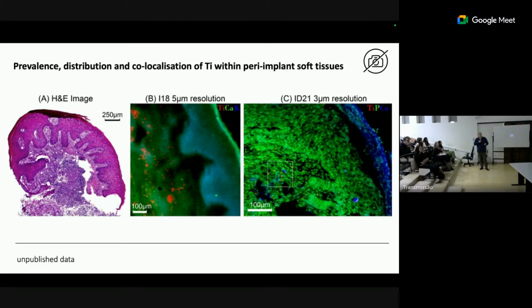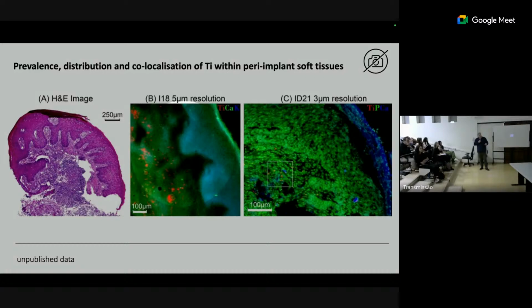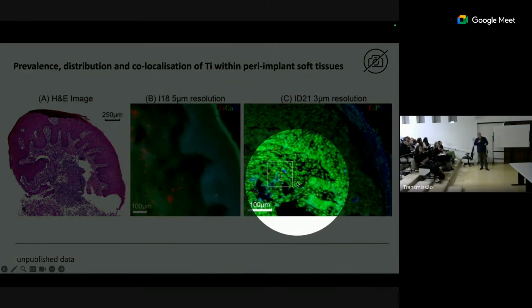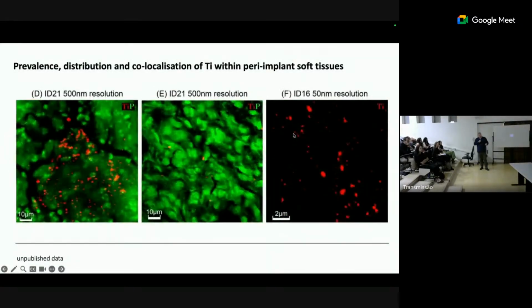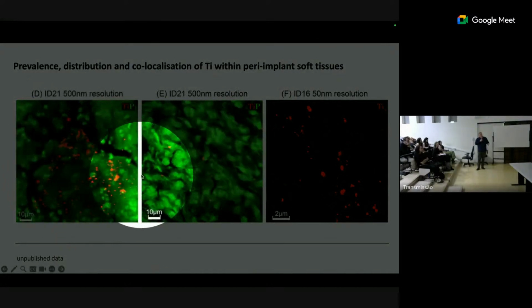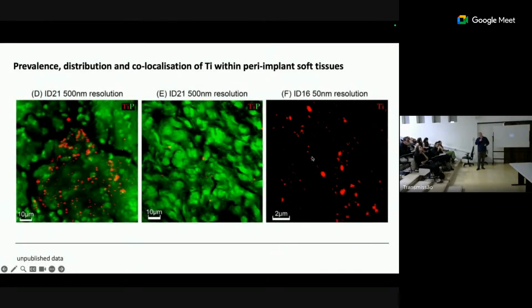And then we go to higher resolution on the right-hand side. Again, we see it all subepithelial, and we're starting to see something to do with the size. We go down even to further resolutions using different instruments. Sometimes we see granulomatous type formations that we've correlated with histology. But the key thing is when we go again to the highest resolution that we can, here this is at 50 nanometers, we see individual particles.